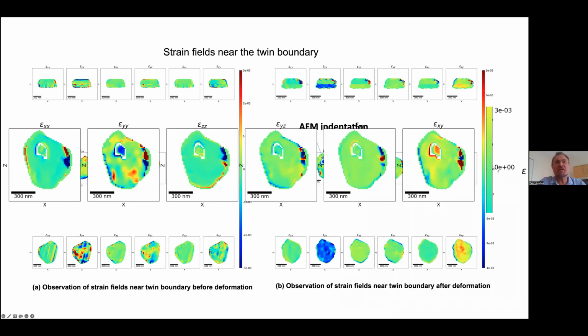Okay, thank you both. And the reason why I'm asking is that in high pressure experiments on large plastic deformation, we are getting a reduction in phase transition pressure by a factor of 10 to 100. Oh. Yes. And the only way I can imagine is that plastic strain injects dislocation pileups, and at the tip of a dislocation pileup, you have very strong multiplication of stresses, and that is what causes phase transition at lower applied pressure. And we have proof, theoretical, analytical, with two different phase field approaches, with molecular dynamics and with concurrent MD and finite element continuum approaches.